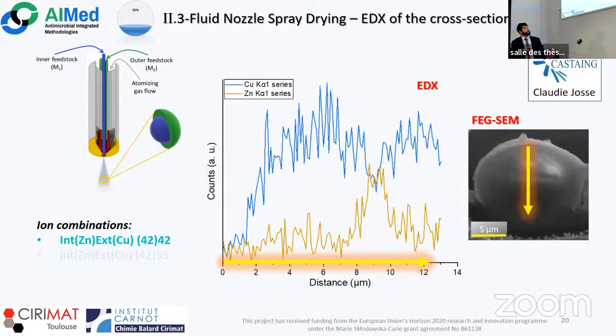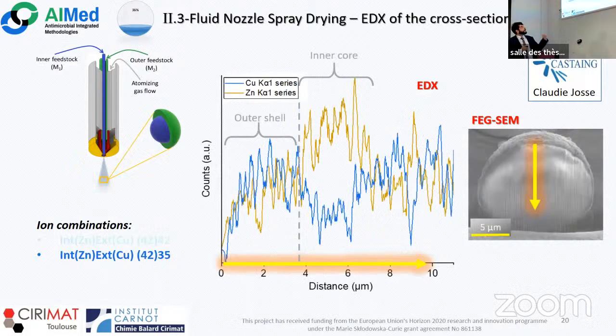So at first, we observed by the EDX analysis of the section of the particle that had the 2 gels at the same concentration that we hadn't a real separation of the inner structure in the EDX. We see copper almost everywhere and a tiny increase of zinc, but that is not that good. On the other hand, when we had the core at a higher concentration, we observed a very nice isolation of zinc in the inner part of the particle, with the shell that is enriched with copper, and unfortunately with not much more information, because the technique is nice, but it has 2 limits.